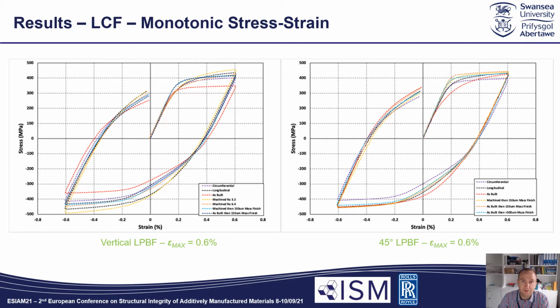Looking at the hysteresis stress-strain loop response, what we have here are the first monotonic loading cycles for each of the different finishes under the 2 different build orientations, with again the verticals to the left and the 45s to the right. Again, all specimens were subjected to a maximum strain of 0.6%, and the graphs show that the Young's modulus values are pretty consistent throughout, with the as-built specimens given in red here appearing to yield first, as would be expected when looking at the stress evolution plots on the previous slide.